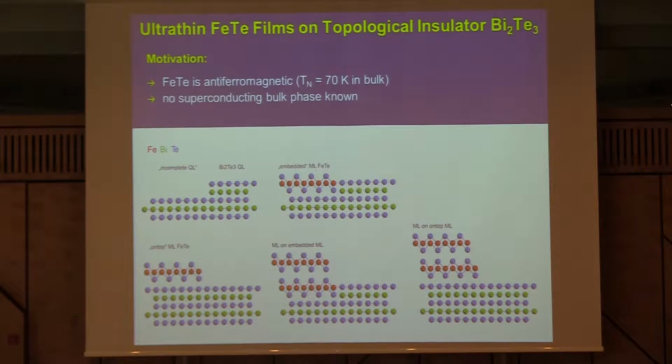However, I would like to stress that the world of antiferromagnets is, of course, not limited to simple transition metals. The next case I would like to discuss is the compound iron telluride. Why is that? Because it's the parent antiferromagnetic compound of very interesting superconducting materials these days. If you dope the system with selenium, you can turn this antiferromagnet into a very nice superconductor.